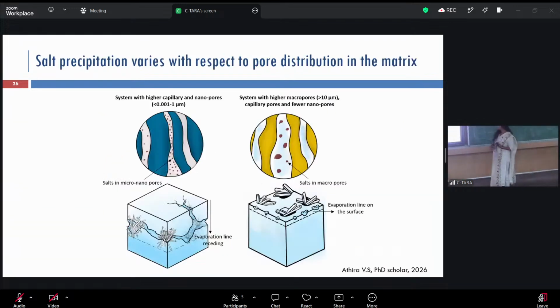So here I have tried to summarize it in some way. This is a jaggery added system. And this is the work from one of my other PhD students. In a jaggery added system, you are having larger pores which are very uniformly distributed because of those calcium hydroxide attached with jaggery molecules. And there, during evaporation, the movement of salt and water is very normal. It comes till the top and you are having an evaporation front here. If this is the lime mortar cube we are testing, your evaporation front is close to surface. You have efflorescence. It is not damaging the material.